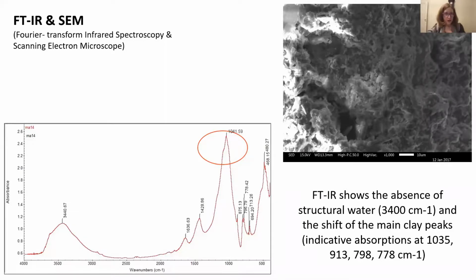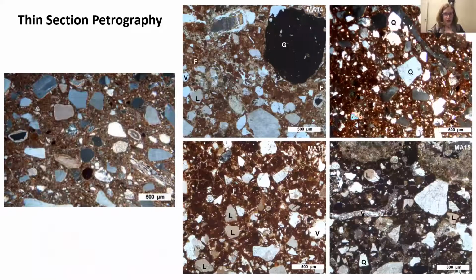The final phase of the geoarchaeological analysis was the petrographic study. And this indicates the presence of a main fabric, which is characterized by a reddish-brown matrix and a limited number of inclusions. These inclusions are mainly monocrystalline and polycrystalline quartz, feldspar, iron oxide nodules, and clay pellets. The presence of a human-induced tempering, such as lime fragments, was also documented.